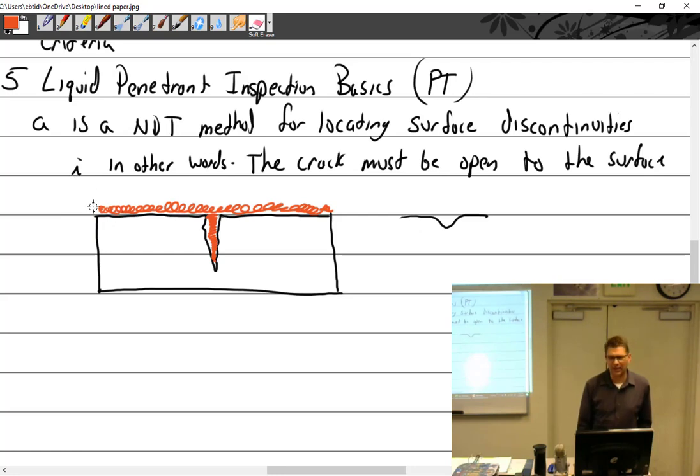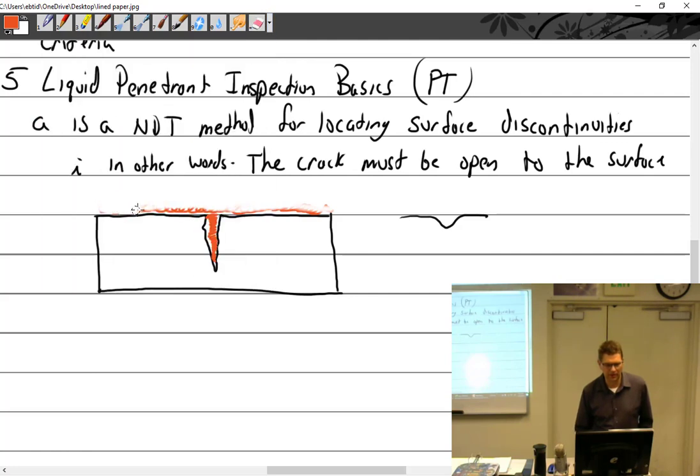Okay, we got to remove the excess. It is dry, wet, dry. So if we're using this process here, we use a dry towel and we wipe off as much as we can. Now, if I only do that much, I'm going to get red everywhere. So it's not really easy to do this. All right, dry, wet, dry. Use a dry cloth, dry cloth, dry cloth, using a new piece of the cloth every time. Then we'll do a wet, the solvent on the rag, and then one more dry.